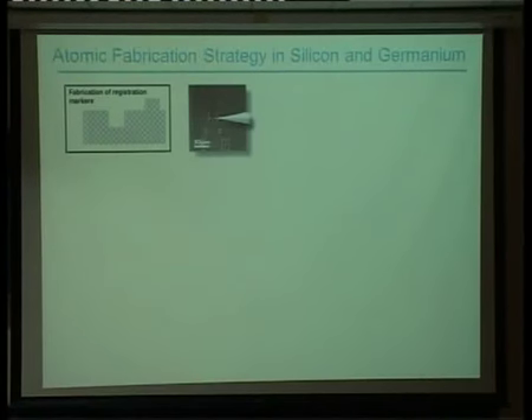So very quickly, I know a lot of people in the audience have seen this before. Basically, the key thing about trying to make single atom devices in silicon is you have to use the scanning tunneling microscope to precision place them inside the silicon crystal. You can see it inside the microscope, but you can't see it outside. So that was one of the challenges to actually make atomic scale devices.